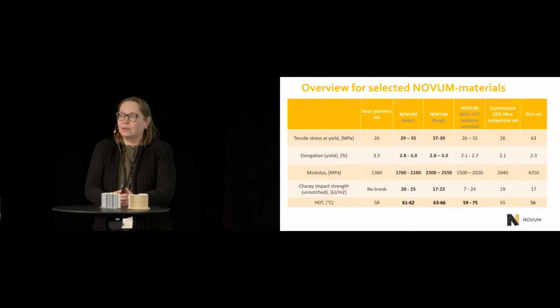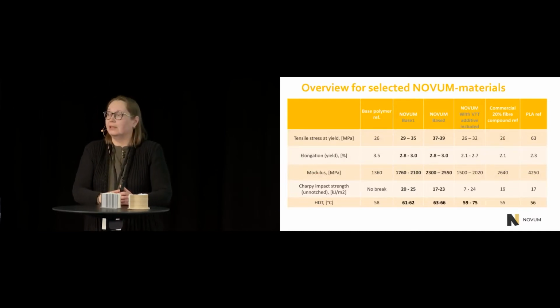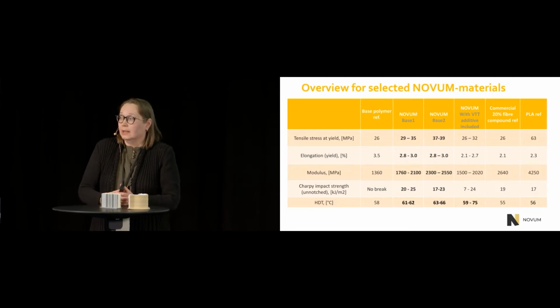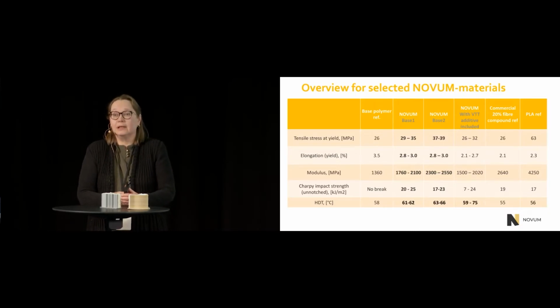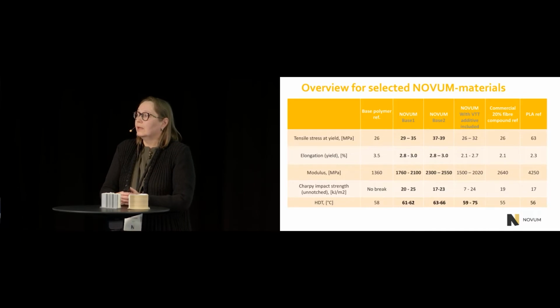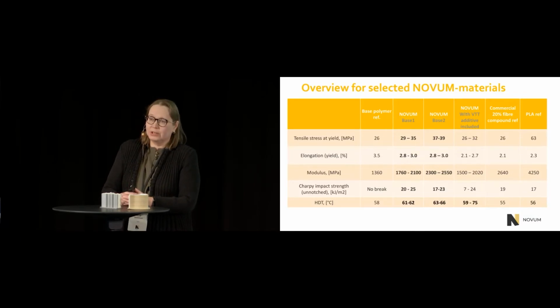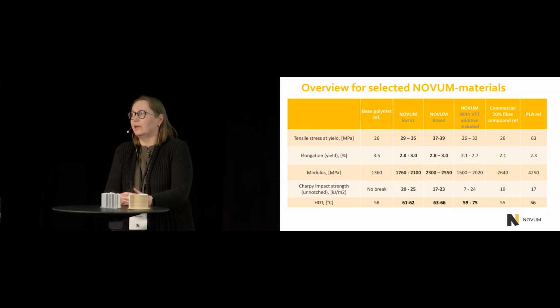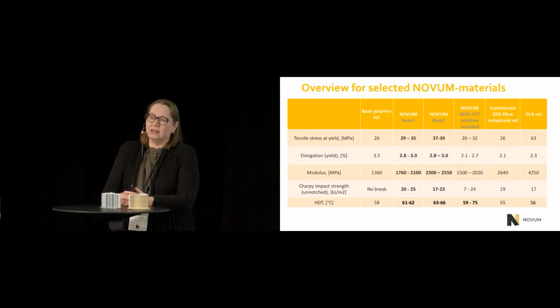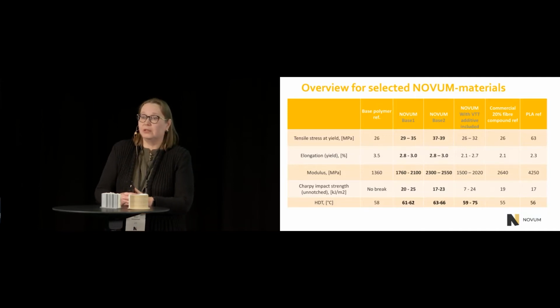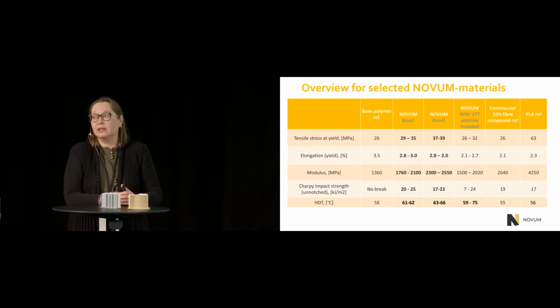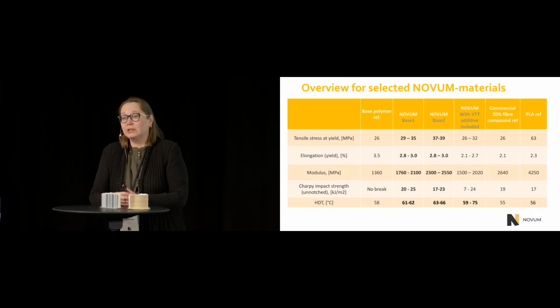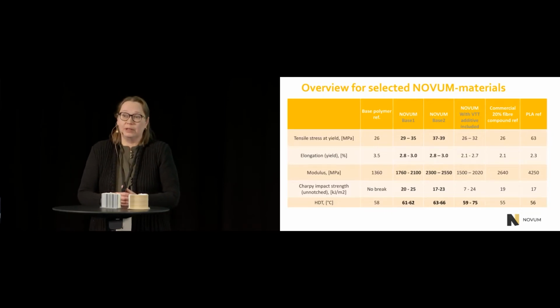Then a bit of an overview of the selected NOVUM materials we have developed here. And we actually see 3 different base material properties here. And one of them is containing this VTT thermocell additive also. And if we compare those materials to the commercial 20% fiber containing compounds, mainly containing PLA or something like those as a base material, we can see that in all materials the mechanical properties are, let's